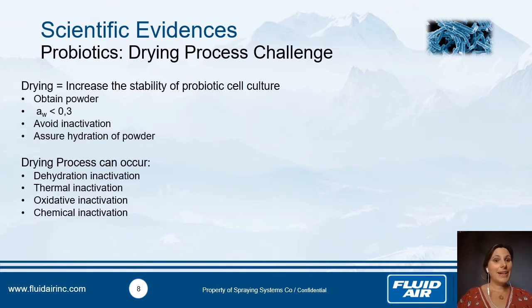So drying probiotics is a little bit challenging. Why do we want to dry? It's to increase the stability of probiotics, but the main point is to obtain a powder. The second point is to have a water activity below 0.3, and we have to avoid all the inactivation that we can have with probiotics and bacteria in general, and also to assure a good hydration of the powder when we want to reconstitute it. So what happens when we want to dry? You can have dehydration, thermal, oxidative, and chemical inactivation. So you have to be really careful when you dry to avoid all of this inactivation.